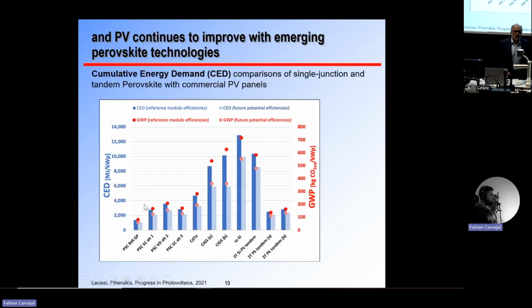Now, these improvements on energy payback times continue with emerging technologies like perovskites. And you can see here, this is a little busy slide. Here, these very low numbers correspond to 4 single junction perovskite technologies. One is the roll-to-roll gravure printed type of technology on a flexible substrate. And then we have 3 technologies on rigid glass substrate, 2 spray coating, 1 with vapor deposition. And here at the other end, we have 3 tandem technologies. They all have much lower cumulative energy demand than silicon or thin films.